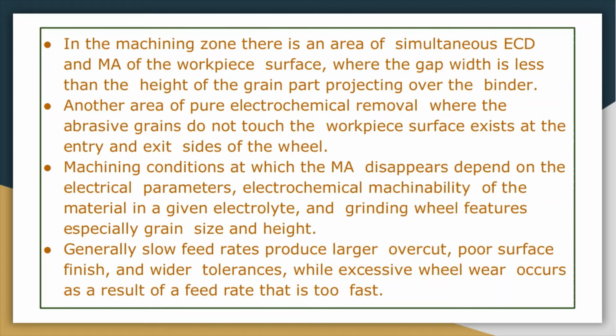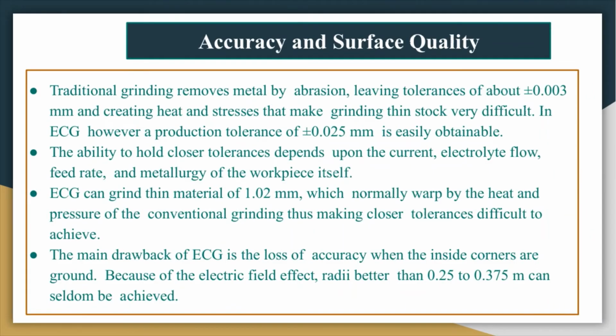Now, the machining condition at which the mechanical abrasive disappears depends on the electrical parameters, the electrochemical machinability of the material in the given electrolyte, and the grinding wheel features, especially grain size and height also. Generally, slow feed rates produce large overcut and poor surface and width tolerance, while excessive wheel wear occurs as a result of a feed rate that is too fast.